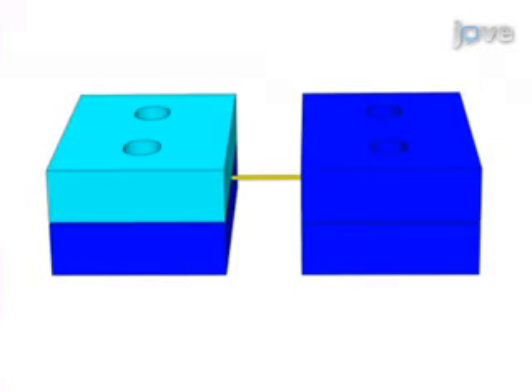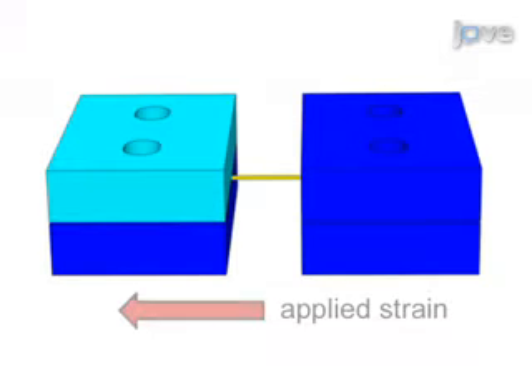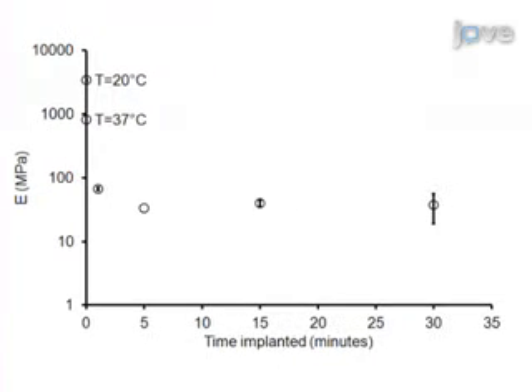The final step is to load the sample into the environmentally controlled microtensile tester and perform the mechanical testing to determine the Young's modulus of the material after the specified implant duration. Ultimately, this environmentally controlled microtensile testing is used to show the changes in mechanical stiffness as measured by Young's modulus as a function of time exposed to the physiological environment.